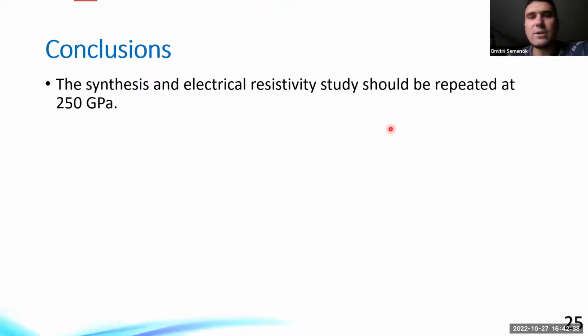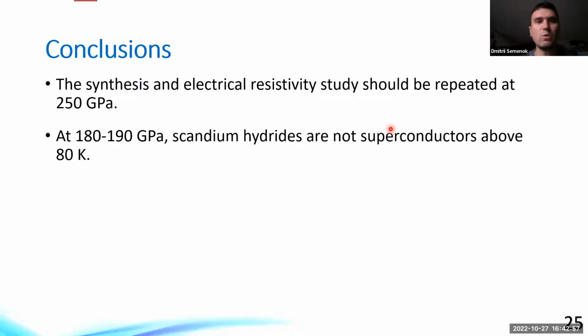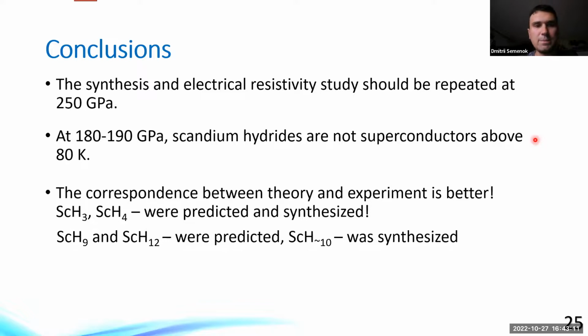Okay, so again, for scandium, as for magnesium, we should repeat the synthesis and the electrical tests at pressures of 250 GPa at least. We need higher pressure, lower weight, and smaller atomic radii. It means we need to apply more pressure to form superhydrides and to convert them to atomic hydrogen superhydrides. At this pressure, about 180-190 GPa, scandium hydrides are not superconductors above 80 kelvins.